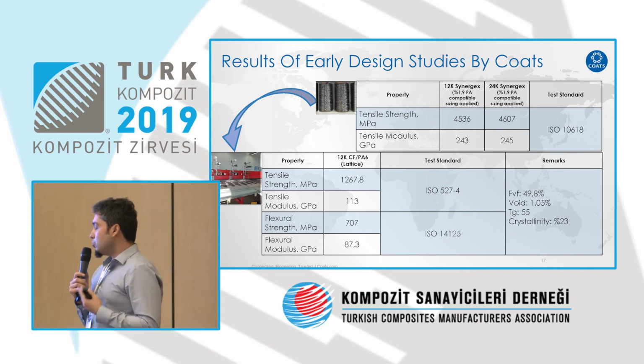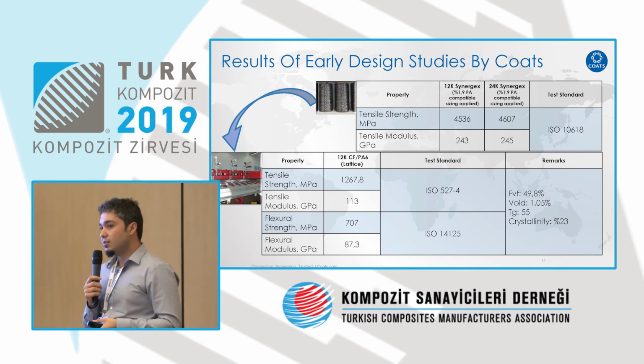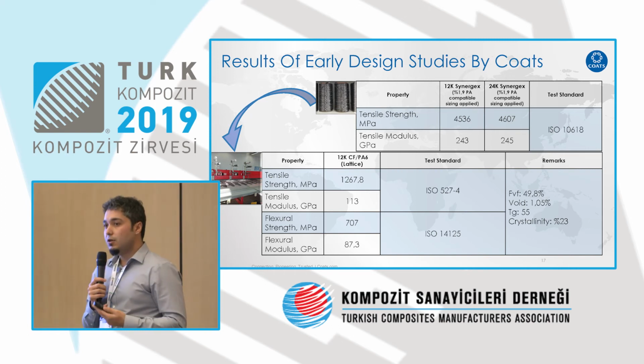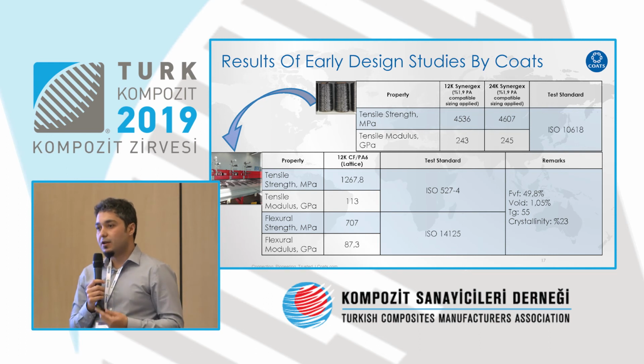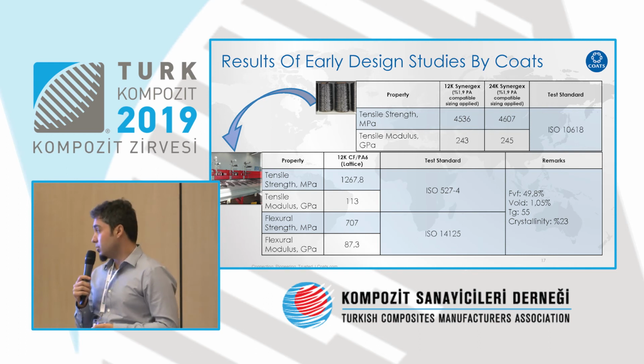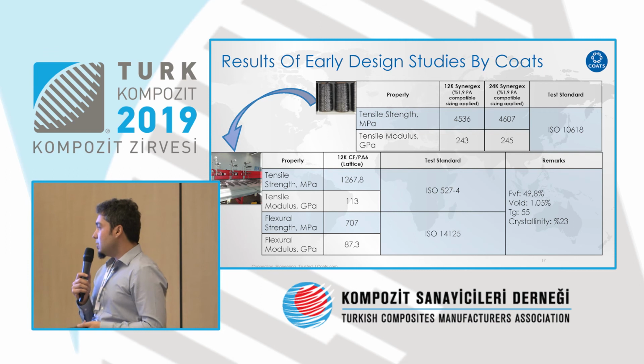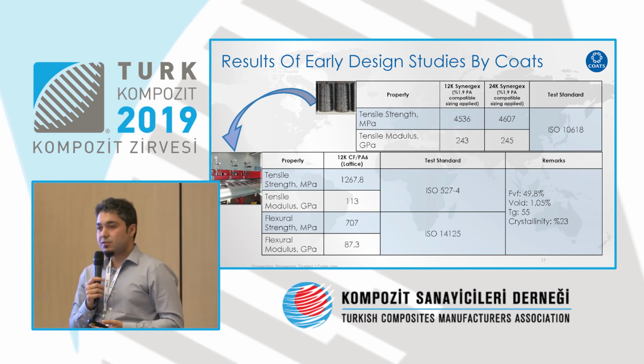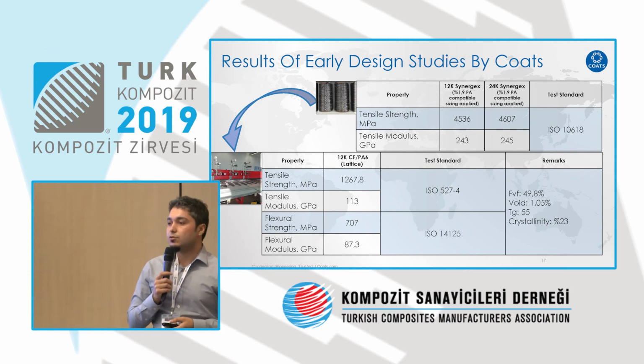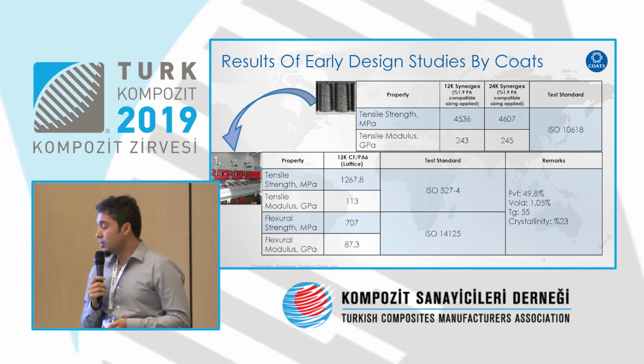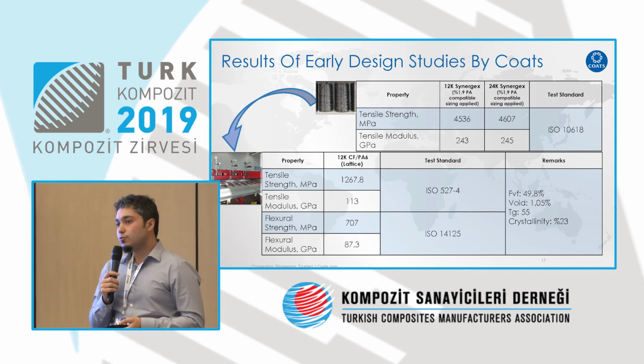Fiber content was produced for 50%. The real value measured was 49.8%. We look at the void values. It was around 1%. The Tg of the nylon was 55, and the crystallinity value was around 23%.